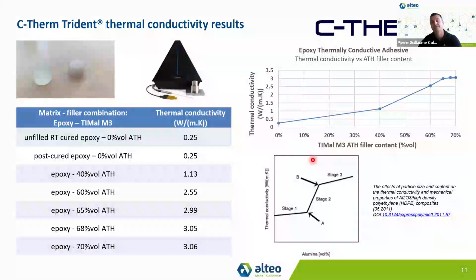And on the right-hand side, I have put a small publication, which is relevant here, where you can clearly distinguish 3 steps when increasing the filler content in your polymer matrix. The first one, you just increase slightly the thermal conductivity. In fact, your particles are just surrounded by binder, but individually in between the matrix. Then you increase sharply the thermal conductivity, which means the particles are now touching each other. So you are creating a thermal pathway, so heat dissipation is more efficient. And after the percolation threshold, you have stage 3, where you have already created a lot of thermal pathways, and you are just creating some new channels, let's say.